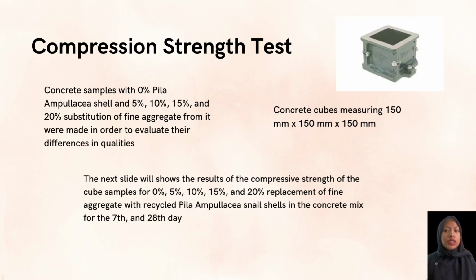In addition, we will use the compression strength test, in which a concrete sample is substituted with fine aggregate of Pila Ampullacea at 5, 10, 15, and 20% in order to evaluate the difference. The cube that we use measures 150 millimeter by 150 millimeter by 150 millimeter. The next slide will show the result of the compression strength of the cube samples with 0, 5, 10, 15, and 20% replacement of fine aggregate with recycled Pila Ampullacea shell in the concrete mix for 7 and 28 days.